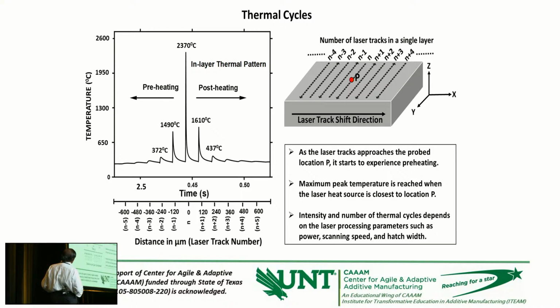So on this side you get a preheating effect. As the laser beam comes here, it starts hitting these regions, and when it goes past this point, it post-heats this. So the heating keeps going on. Even when the laser beam moves away from this point, it keeps heating this one because of heat conduction. That is called the post-heating effect. And when the laser beam moves from this side to this side, this is called a preheating effect. So the laser keeps hitting the material in that layer while it is going track by track. The laser moves from left to right. While it's moving, it creates the preheating effect. And when it comes to this track, the temperature is highest here, and it starts dropping.